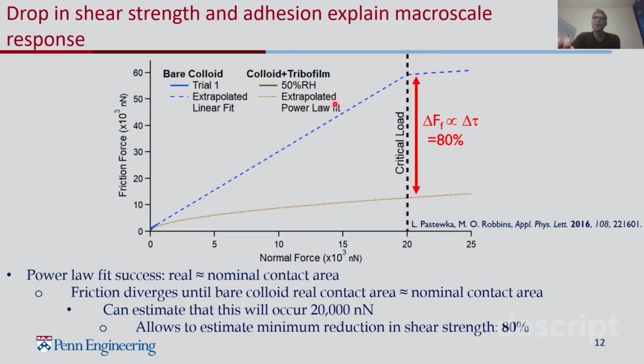And so we know at 20 micronewtons, these extrapolated curves will have the same real area of contact approximately. And so what that means is that this change in friction force between the two is actually equivalent to a change in the interfacial shear strength. What this means is that this tribofilm is providing an interfacial shear strength reduction of about 80%.